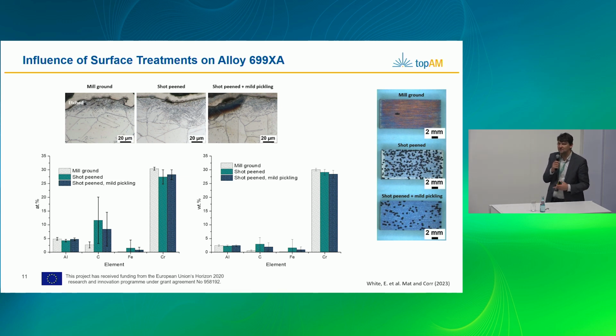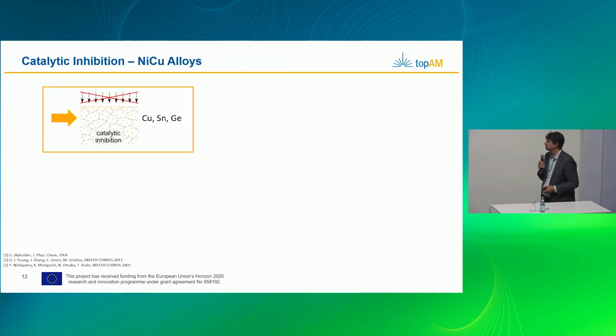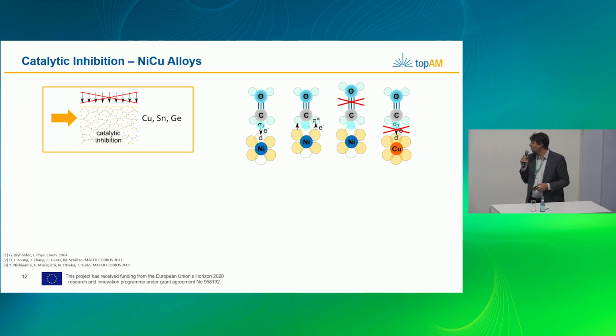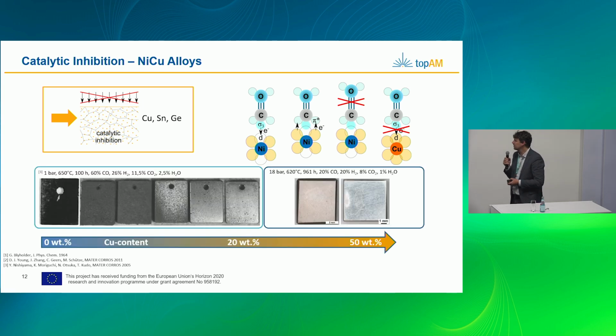So I would like just to raise the awareness that the AM is great, but be a little bit careful in the end when you pick your final treatment, especially when you go to corrosive environments. When it comes to solution annealing as well as the surface treatment. Another approach is, and I showed you this initially, to use a catalytic inhibition. And there, copper is known very well to prevent this attack. The carbon cannot, easily spoken, it cannot really connect to the material once you have copper in there. So that suppresses it.